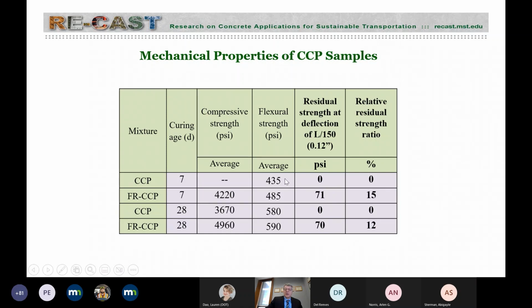With the fibers, you have a slight improvement, about 10%, but the main improvement was the load carrying capacity at L over 150. We got 15% residual strengths. And this is at 7 days, and similar results at 28 days. So at 28 days, the flexural strength was similar with and without fibers. But again, we have that residual strength, that 12% with the fibers.